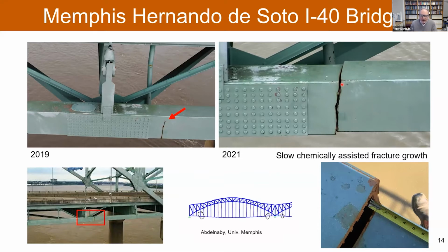It grew over time. It probably grew by the chemical assistance of the oxidation here. So this is slow chemically assisted fracture growth. They think it started actually when the bridge was new. There was a welding flaw, and that flaw, all those years, it was built in 73, I believe, over the 50 years has allowed the fracture to go across. Well, envision that a caprock may be just like this beam here. A fracture could grow in a chemically reactive environment. The humidity in the air and the rainfall would be sufficient. And then over time, very slowly, a fracture propagates across. Okay.